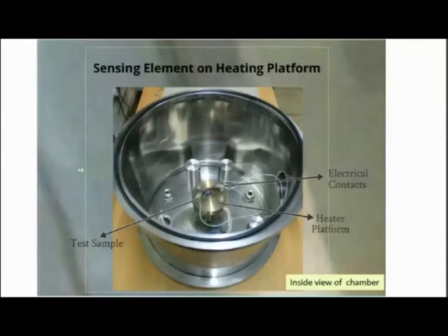So for that we have a platform here which does gas sensing inside a vacuum chamber, which has a heating stage. Remember, all these elements are highly sensitive at a higher temperature. That is the biggest problem with gas sensing, that particularly semiconductor metal oxides or even metals, they cannot sense so well at room temperature as they can sense at slightly elevated 190 degrees, for example, or 180 degrees temperature. In the present case, it will be about 180-185 degrees, at which sensibility will be the highest in this particular case.